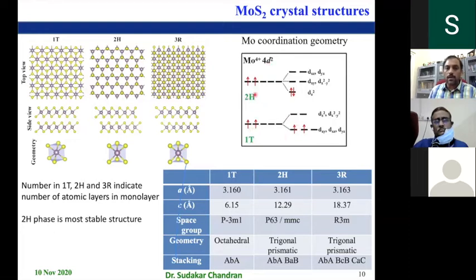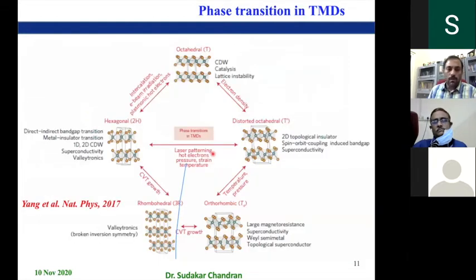Whereas in its trigonal prismatic configuration, the crystal field is such that you have a low spin configuration. Therefore, these 2 spins will get paired up, and therefore it exhibits diamagnetic characteristics. So the 1T phase can be made into a ferromagnetic state. So there is a lot of interest in how to alter the 2H to 1T phase in a stable manner at room temperature. That is the kind of study a lot of people have taken up.